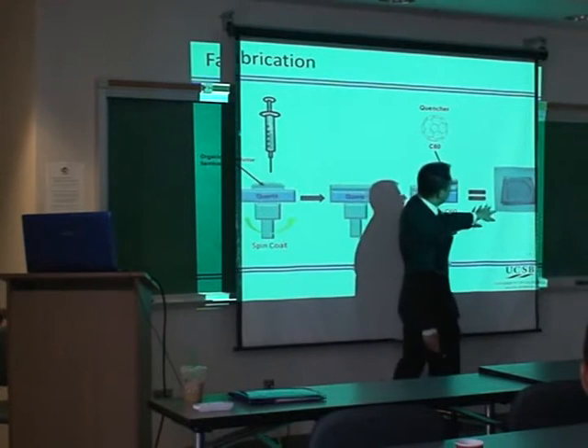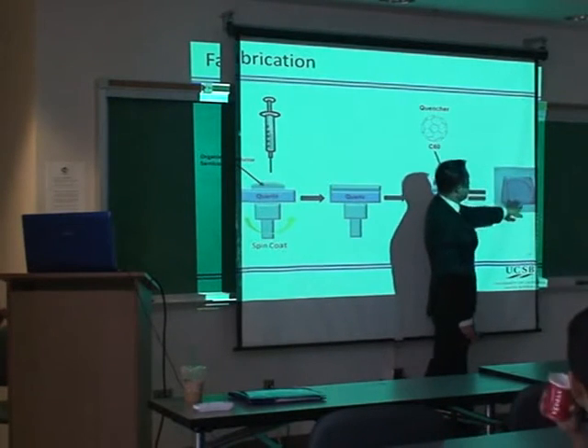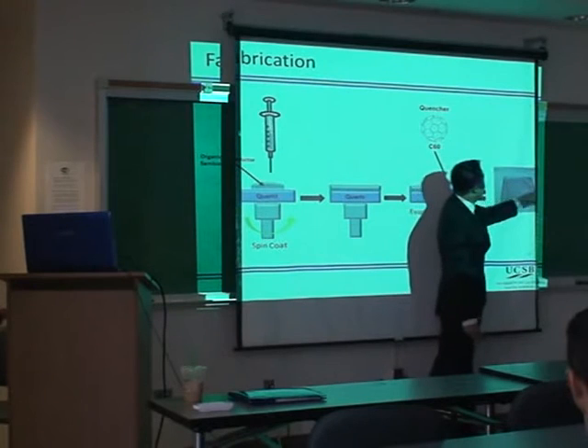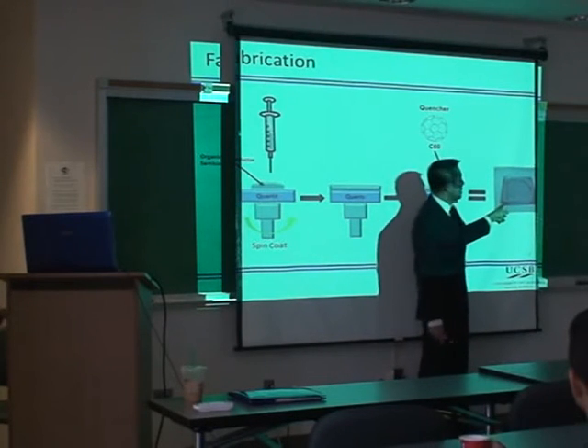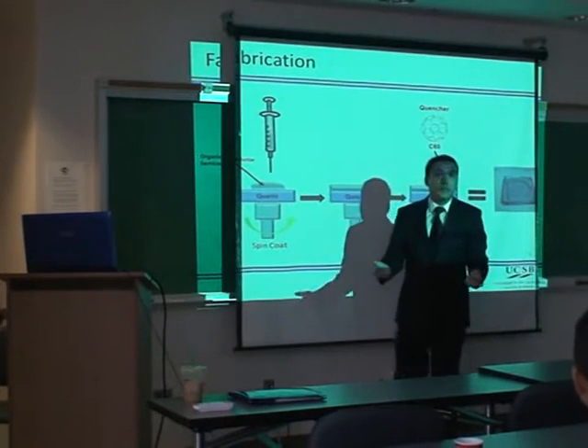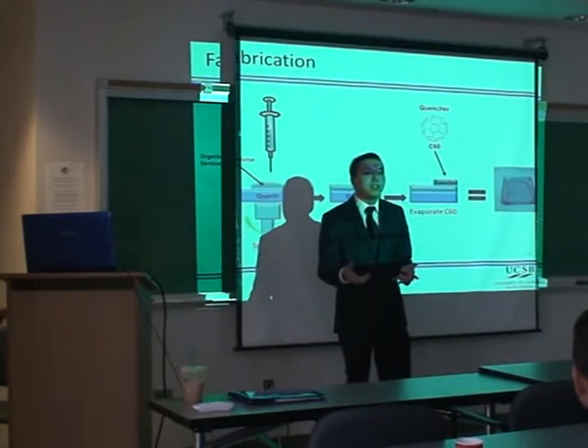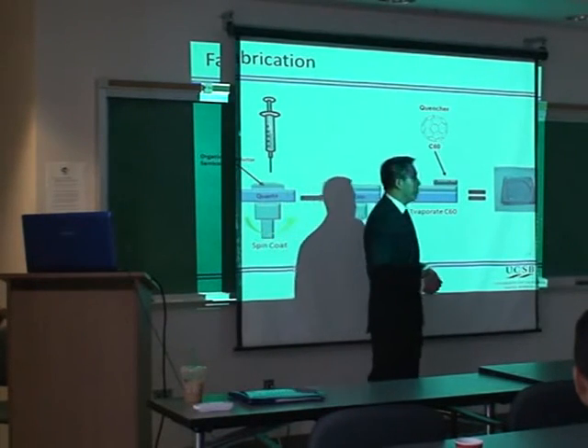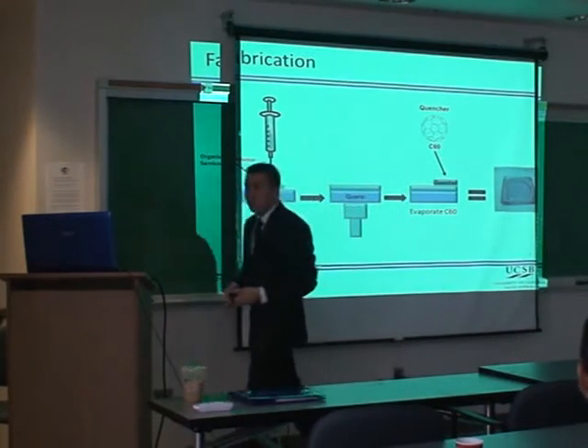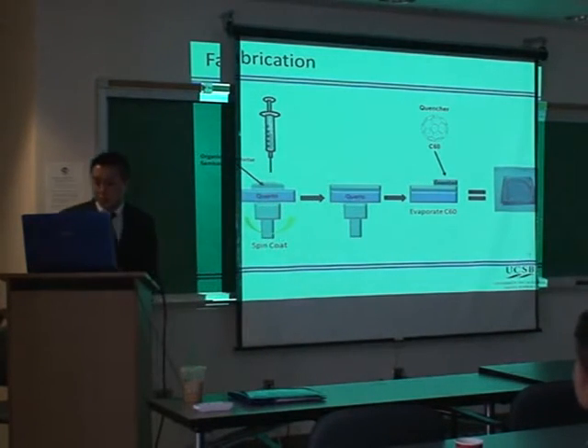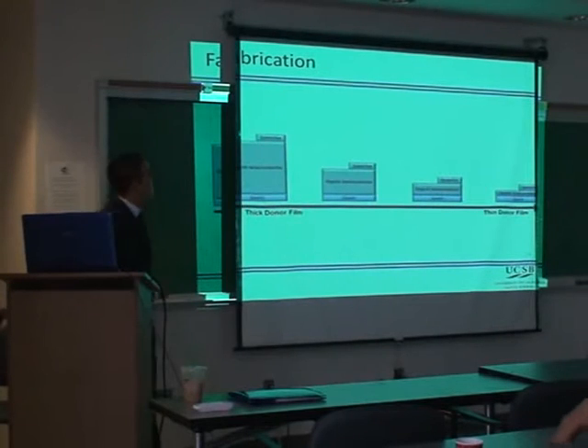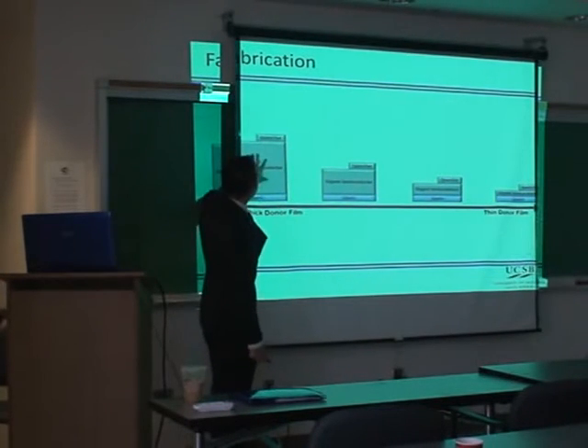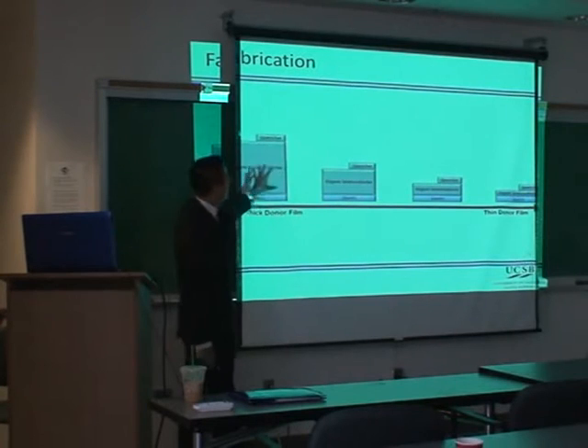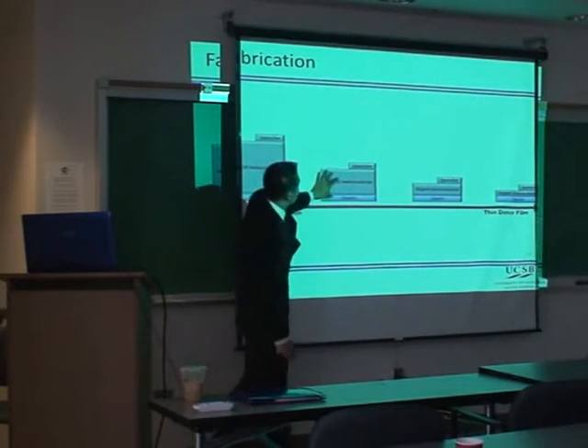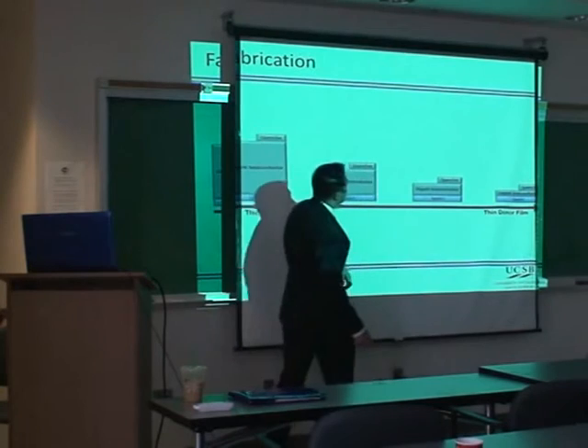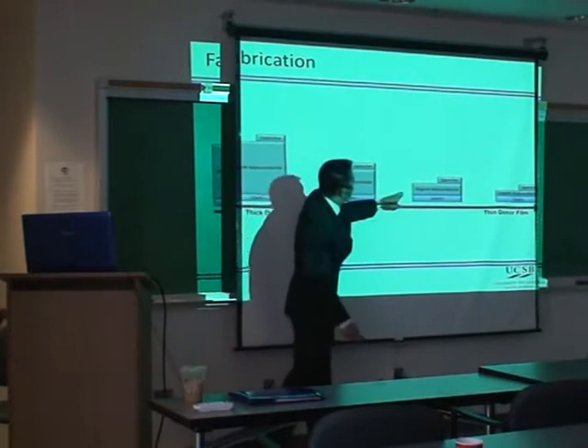And then the final form of how these films look is basically like 2 pieces of glass glued together. This is like epoxy. This is actually really important because a lot of these organic films are very sensitive to oxygen. If you excite them with light and you expose them to oxygen, it's very likely that they're going to photodegrade. And that might change the chemical structure and reduce the lifetime of these materials. So what we then do is we change the concentration of the solution, and by doing that, we are able to produce different thicknesses of the organic layer. So you can see we have thick films, and then as the film thickness decreases.